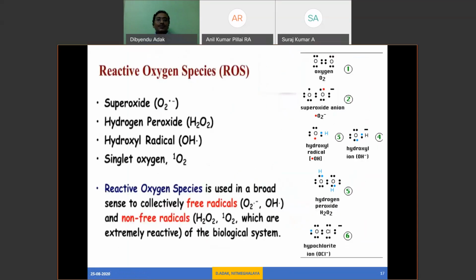And reactive oxygen species also, as I told you, there will be the superoxide. These are reactive ions and free radicals, which will initiate the destruction of the bacterial cell. That may be the superoxide ion, oxygen with one unpaired electron. There may also be hydrogen peroxide. Hydrogen peroxide is a non-free radical, and superoxide and hydroxyl radicals are free radicals. They will kill the bacteria by increasing their oxidation rate.